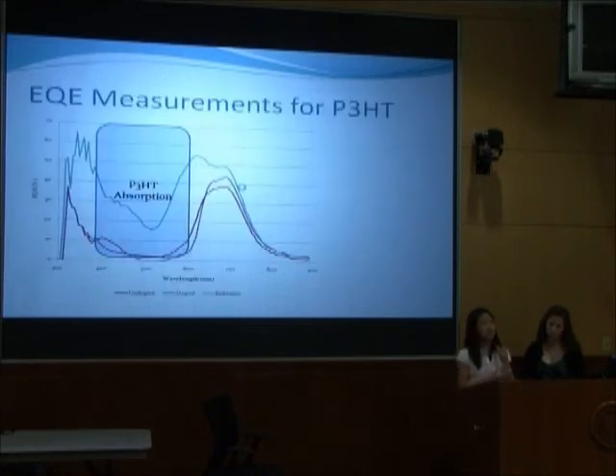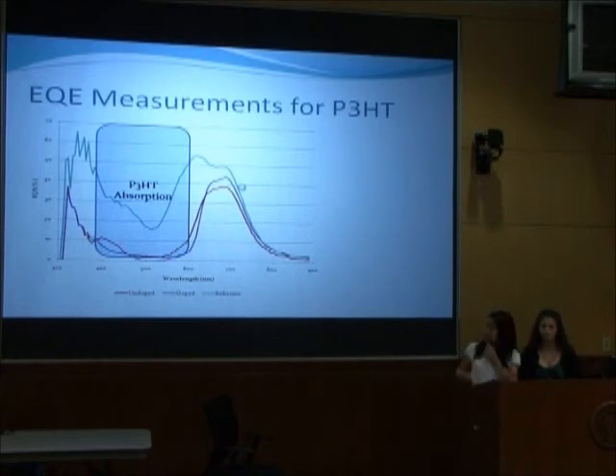However, why do we not use P3HT, and why do we want to test TAPD? This is because P3HT absorbs a lot of light. This is an EQE plot of P3HT. EQE is external quantum efficiency. It's simply the percentage of incoming photons that actually end up generating an exciton pair, which leads to charge generation. But as you can see, the P3HT absorbs the light from 400 to 600 nanometers here, and because of that, it's limiting the amount of current that's being generated. TAPD, on the other hand, is transparent and does not have this disadvantage.